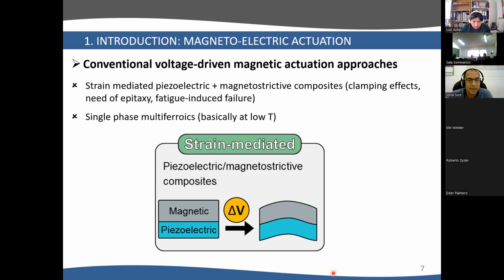used effect is the piezoelectric magnetostrictive effect in composites or bilayers, where you apply a voltage, then the piezoelectric deforms, and adjacent to this piezoelectric there is a magnetic layer which also gets deformed, and due to the inverse magnetostriction effect there are changes in the magnetic properties. The problem of this mechanism is that if you grow this bilayer on top of a rigid substrate, the amount of strain can be limited due to clamping with the substrate, which is rigid, and if there is no strain, there is virtually no magnetoelectric effect. Then if you have a self-standing structure, the problem is another one: after actuating and deforming it many times, at some point there can be fatigue problems and the two layers can become detached.